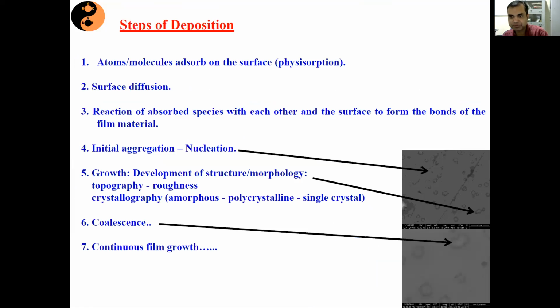So these evaporants, when they reach the substrate, they first try to get to thermal equilibrium. They are adsorbed on the substrate surface. Then, after adsorbing on the substrate surface, they diffuse on the substrate surface from one side to another, until they find the second evaporant, third evaporant, fourth evaporant, and then there is nucleation taking place. And after that nucleation, there is growth around those nucleation sites, and then finally some features start developing, which can be amorphous or polycrystalline or single crystalline. And then these different sites coalesce together to form a continuous film. So these are the steps of deposition.